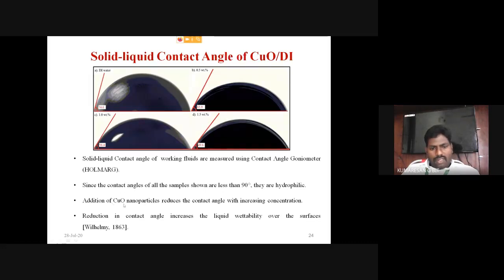That addition of copper oxide nanoparticles reduces the contact angle with increasing the concentration. If the contact angle is reduced, automatically the solid-liquid contact angle is reduced, which means the surface tension between the liquid and the solid surface is reduced. Okay, so this experiment is conducted by keeping the nanofluid droplet over the copper surface, because I have used that copper metal as the outer surface of the heat pipe.